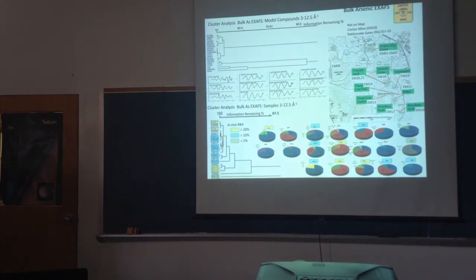Okay, so there's a little more data on this slide, and this will be my last data-rich slide before we wrap up, but I wanted to give you some sense of how we're using data in Empire Mine to understand bioavailability. And it's a little hard to read, and I apologize for that, but we have basically 20 samples that we've characterized with arsenic EXAFS, or extended X-ray absorption fine structure, and by matching the wiggles on these curves to known compounds or model compounds, we've interpreted what's present in terms of the arsenic species. Again, these are samples from throughout the Empire Mine area.